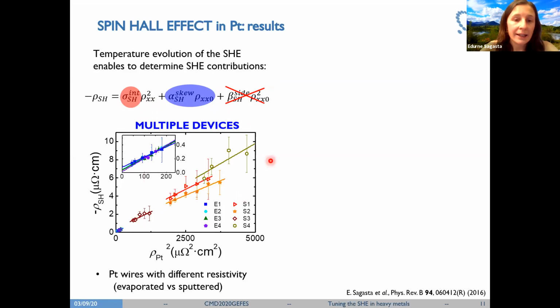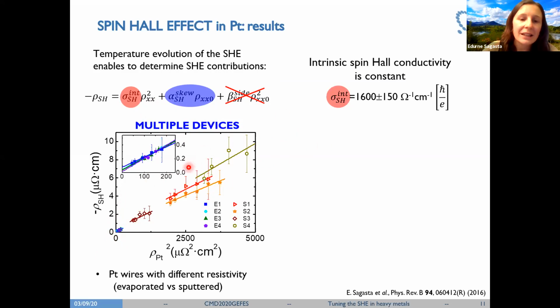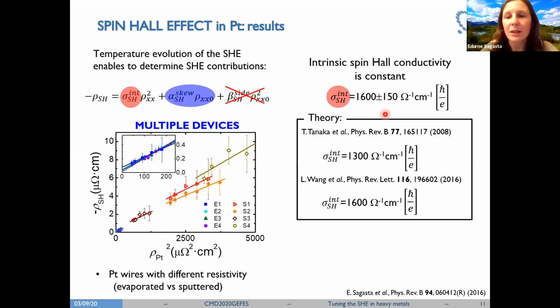So this is the experiment that we did for a single device, but we decided to make more samples. So here we can see the result obtained for multiple devices. We fabricated some lateral spin valves where the platinum nanowire was sputtered, and other lateral spin valves where the platinum was evaporated. They are characterized by lower resistivity, as you can see, the ones where the platinum was evaporated. But interestingly, what we are obtaining, considering all the devices, is a constant intrinsic spin Hall conductivity. We see that the slope inside the error bar is the same for all of them. And we extract a value of 1,600 Ω⁻¹ cm⁻¹, which is in good agreement with the theoretical reports that we can find in the literature.